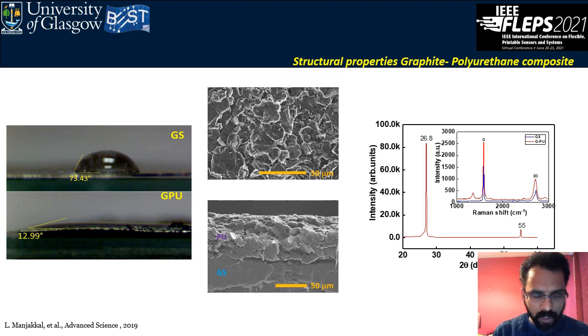Here you can see that we measured the contact angle for a graphene sheet and compared it with the graphite polyurethane. The graphene sheet shows more hydrophobic character. In supercapacitor performance, the electrolyte needs to be properly distributed around the surface. So as compared to the graphene sheet, you can see here that in the graphite polyurethane composite the electrolyte is more distributed. The reason behind this, which we analyzed through scanning electron microscope images, is that the surface of the electrode is rough, with microflakes distributed around the top.